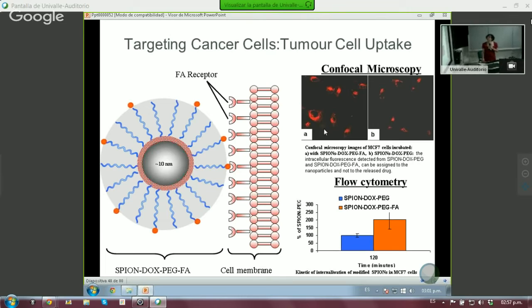So these are the pictures taken by confocal microscopy. It shows you the SPIONs with the folic acid and without, and we see much better results with the folic acid. And when we look here at the percentage of SPION and PEG as a function of time, again, the presence of the folic acid brings a positive element to the picture.